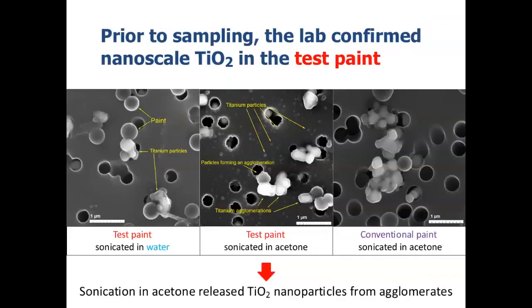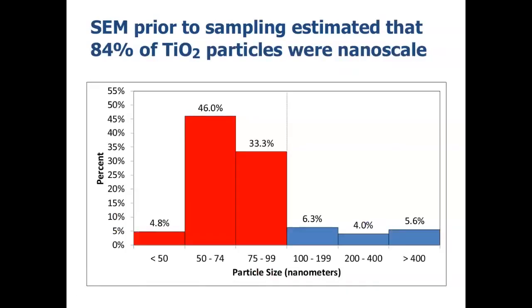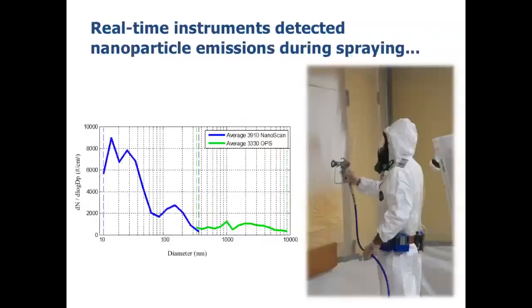Before we did any sampling, we sent a sample of the paint to the laboratory to confirm the presence of nano-TiO2 in the test paint, as shown here in the middle panel. The lab performed the same analysis using a conventional paint of the same brand to confirm that it did not contain any nano-TiO2, as shown in the right panel. Using scanning electron microscopy, the lab estimated that 84% of the titanium dioxide particles in the paint were less than 100 nanometers.